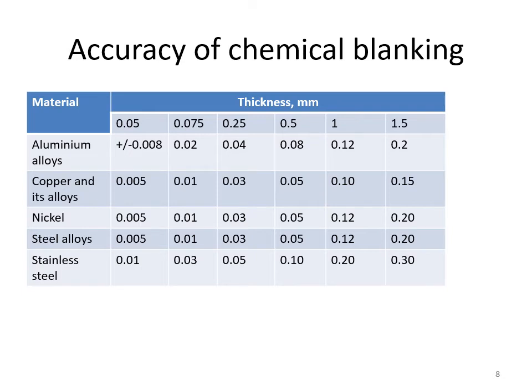Accuracy. Regarding the accuracy, for aluminum alloys with a thickness of 0.05 mm, an accuracy of plus or minus 0.008 mm can be obtained. So this is a very good accuracy which we can obtain during the machining process. The tolerance is to a very great level and is highly permissible, which is why in some cases we take up final finishing operations with the chemical machining process.